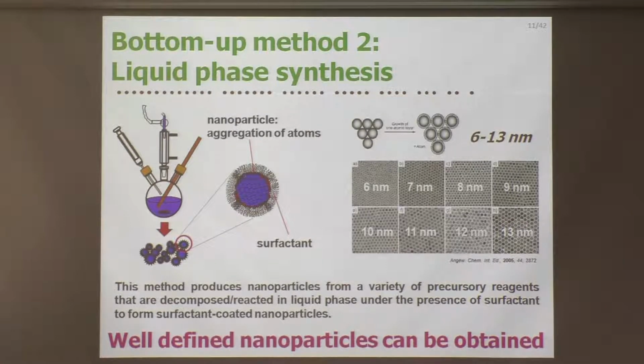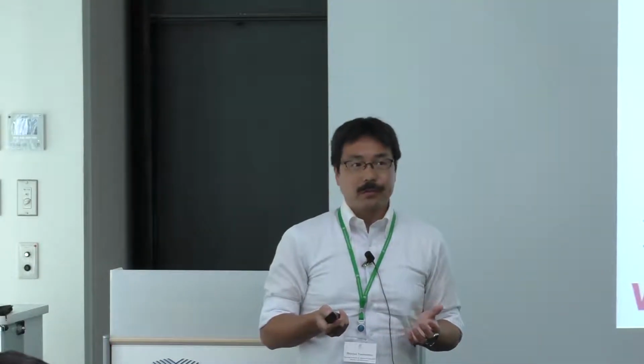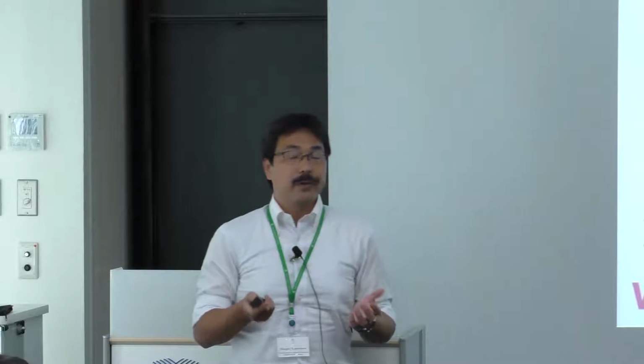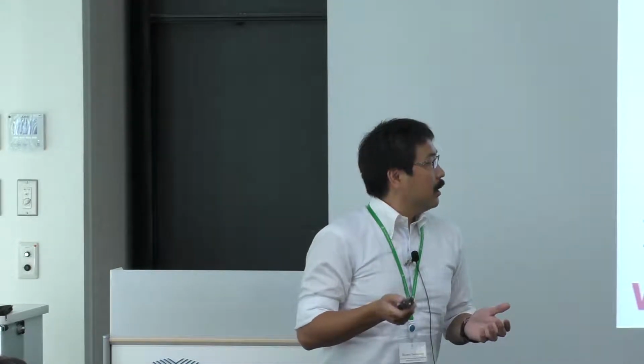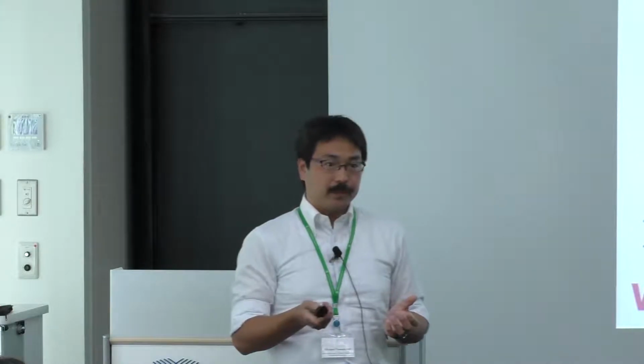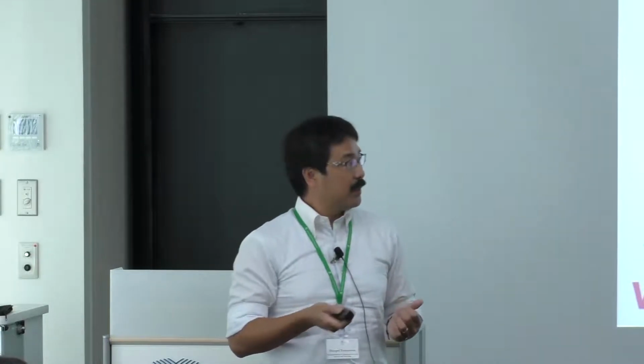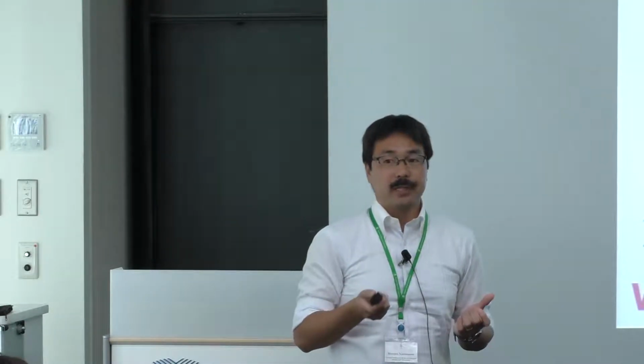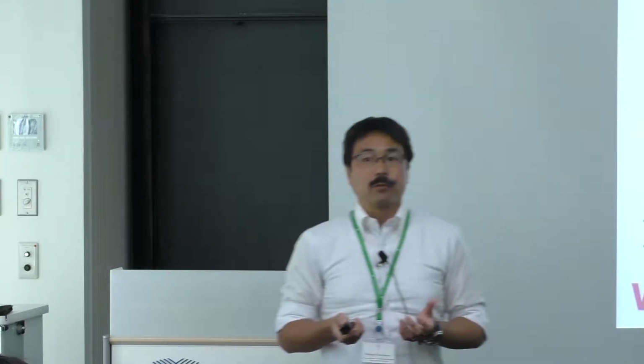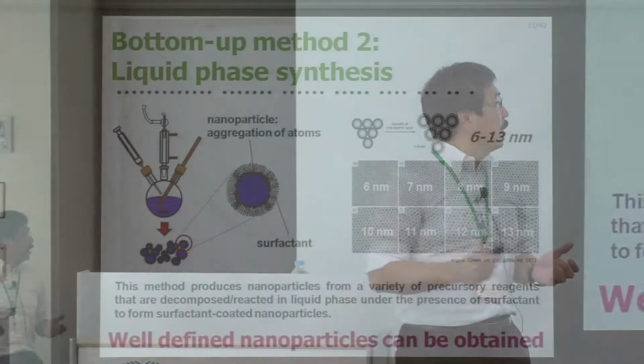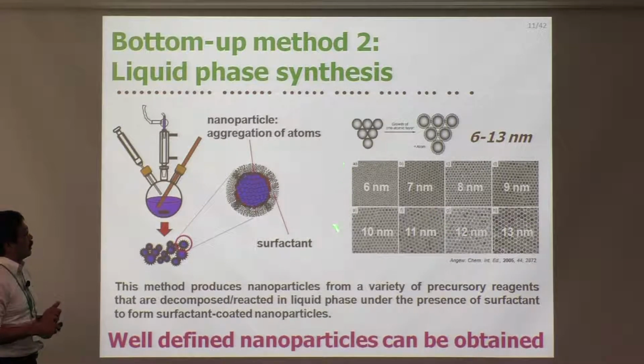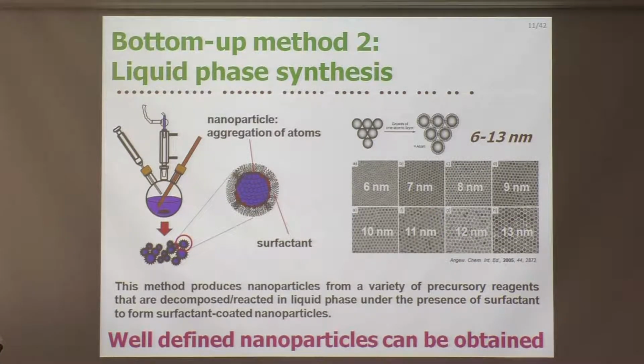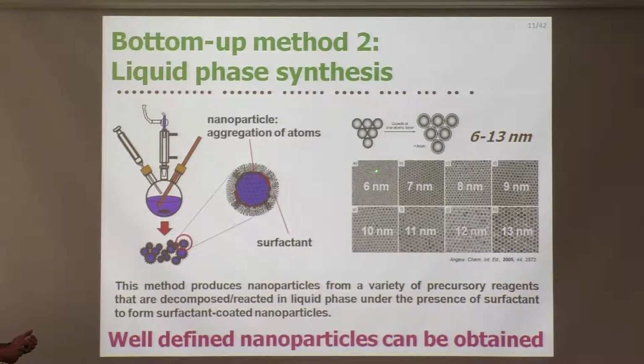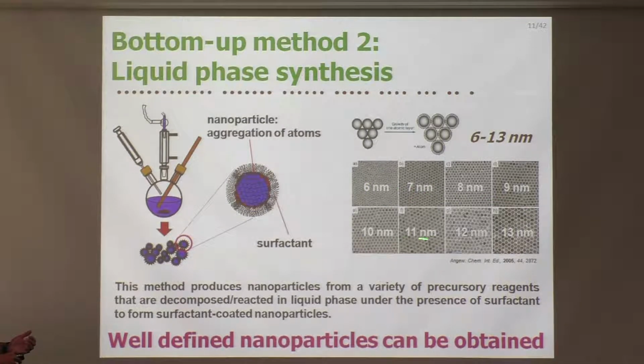And this method is very attractive because the structure of the nanoparticles is relatively easy to control, especially if we carry out the reaction at high temperatures using a high boiling point solvent, typically more than 300 degrees Celsius or so. We can finally control the structure of the nanoparticles. Here shows an example. This is a case of iron oxide nanoparticles. As you can see, the size of the nanoparticles is controlled on a 1 nanometer scale.